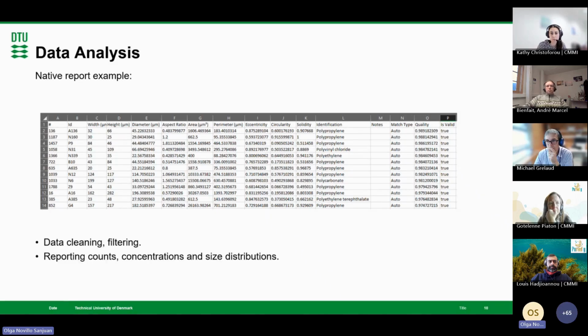After you perform the LDIR analysis, you can export the data as an Excel file with all the information and also with the spectra. And this is what you see in this file, so a lot of really nice info. We need to do a lot of data cleaning and filtering because we normally only take into account matches above 0.8, ideally 0.9, but in environmental samples, it's very difficult to get to 0.9 in my experience. So we normally filter out the data beforehand because we get a lot of particles.